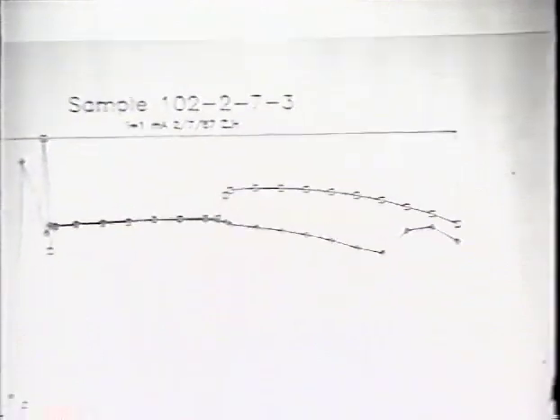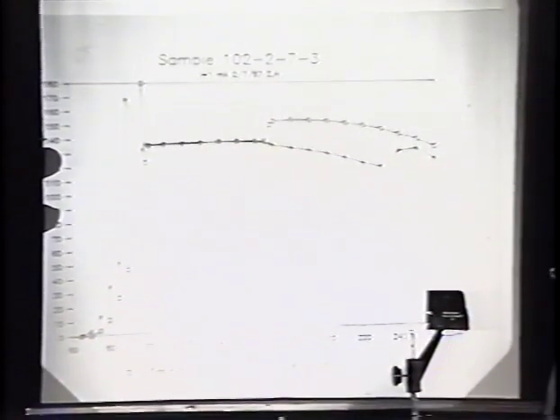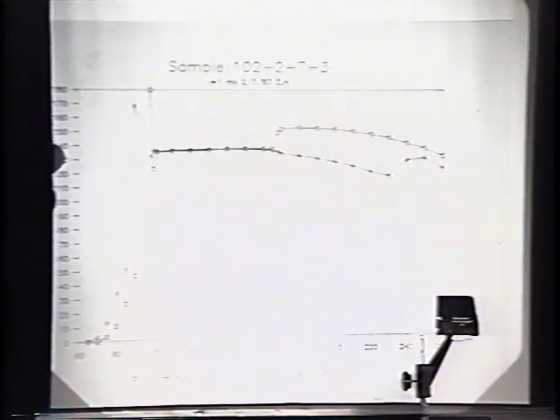attention. Now, one final conclusion. Can we get TC higher? And I believe we will be able to get higher TC. And let me just show you one of the curves here, which is just an indication of superconductivity. In fact, we have seen this kind of drop in resistivity more than 15 times now. And we hope with the hard work of everyone, we can stabilize that phase.